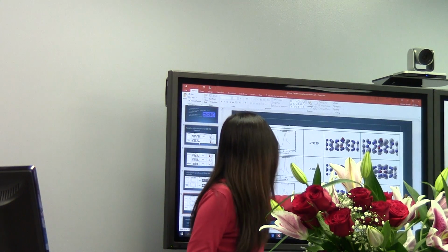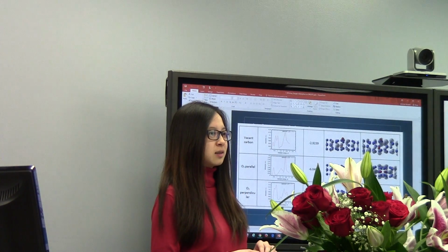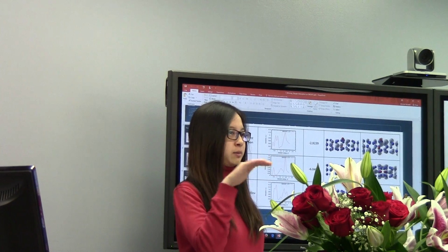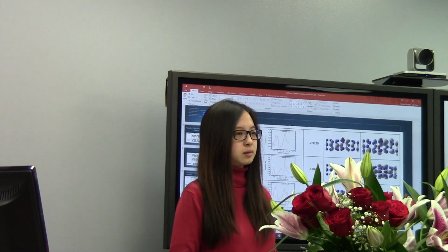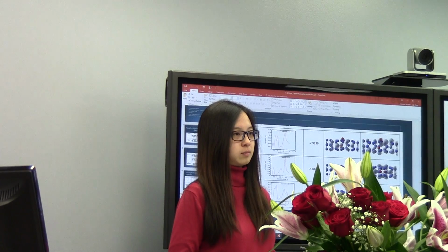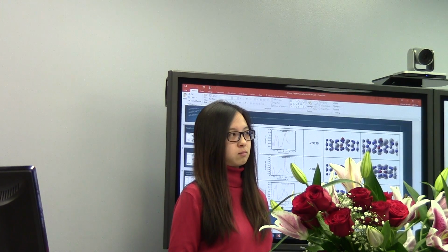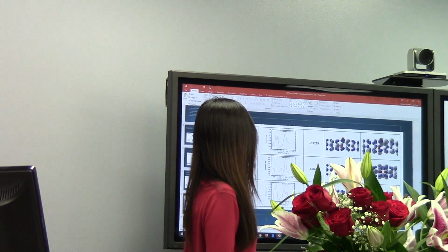For the HOMO and LUMO, it does not change a lot except for this one. It has localized orbitals on the oxygen. In which case, when you substitute or when? No, the one that I put on top, just the normal. So when it's physisorbed, then you have very strongly localized orbitals, and these orbitals introduce this closing or this state inside the gap, right? In the other cases, when it's substituted, it's more delocalized over the surface, although the gap is still changing.